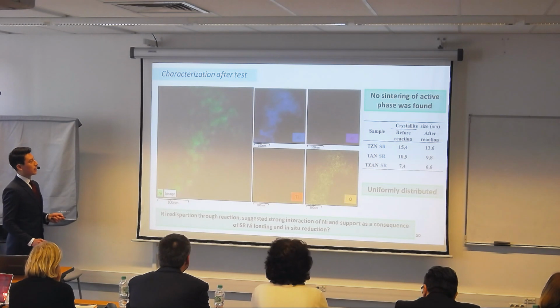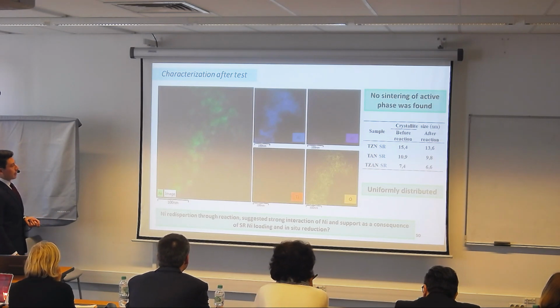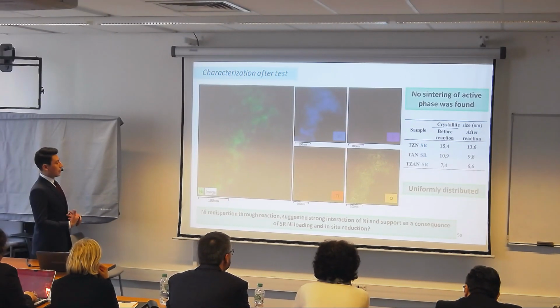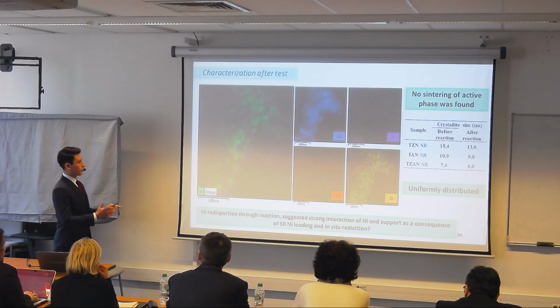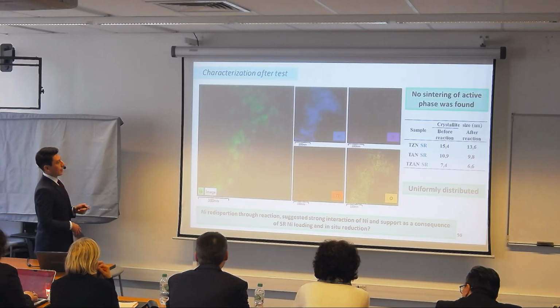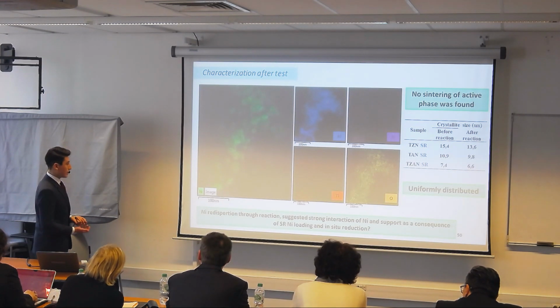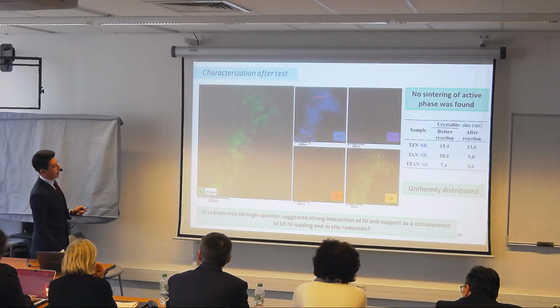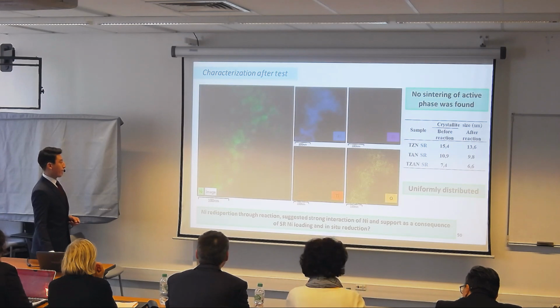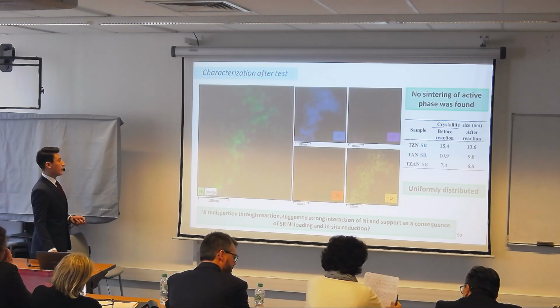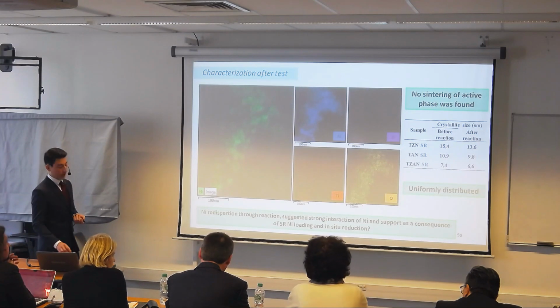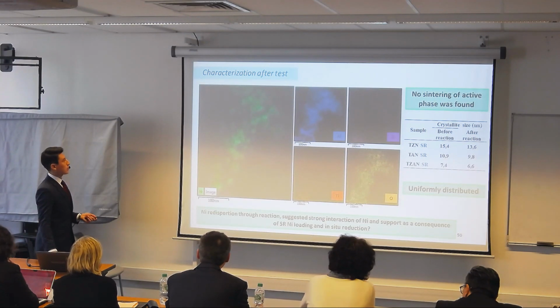We didn't find sintering after the test, but in this case the particles are very uniform on the surface, and we even have a very slight redispersion of the nickel phase. You can see that the values calculated for the nickel crystal size after the test are lower. This suggests a very strong interaction between the nickel and the support as a consequence of this